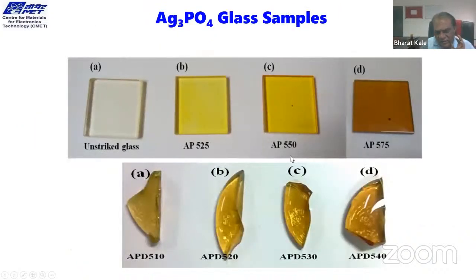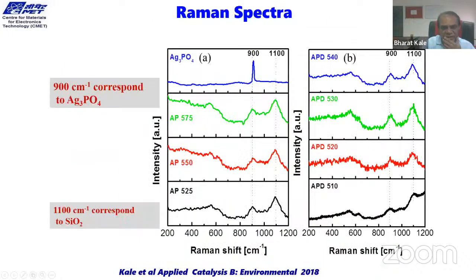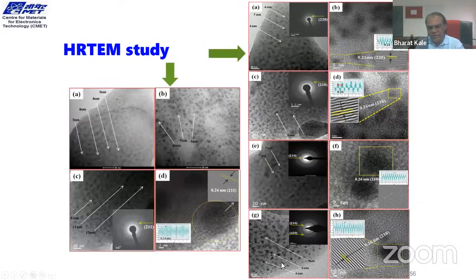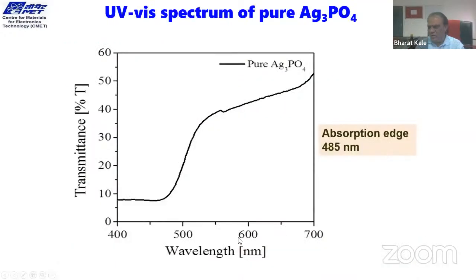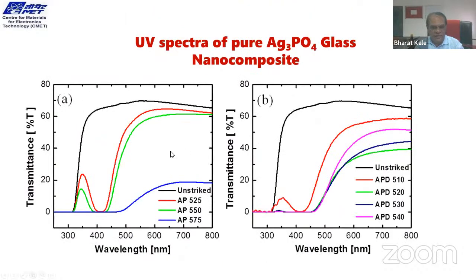You can see the color changes, which means there is a change in the size. And this is a Raman spectra, which shows the formation of Ag3PO4 in the glass. And see here, all these nanoparticles very clearly show that they are highly crystalline. And this is the spectra of the powder of Ag3PO4, which we utilize for the formation of glass.